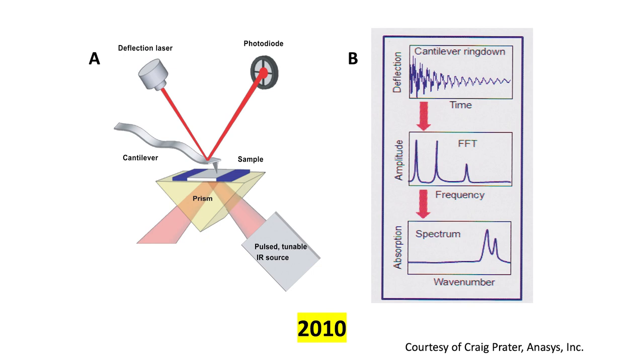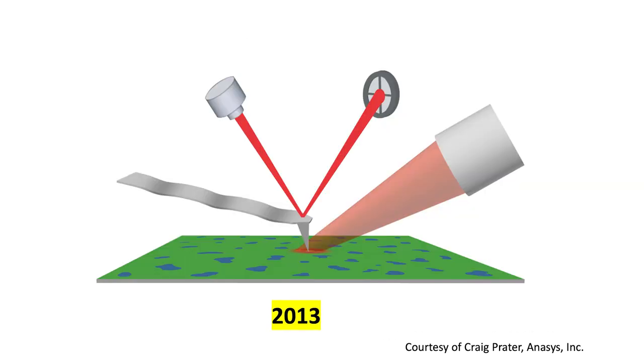The OPO source enabled nanoscale infrared spectroscopy over a tuning range of roughly 1,000 to 4,000 reciprocal centimeters, or 2.5 to 10 microns. In the first design, the beam was brought from the back of the sample and was reflected internally, as shown in this slide. In a later design, the beam was focused onto the sample from the top. Either way, the beam was no longer diffraction limited. Its size was governed by the width of the cantilever.